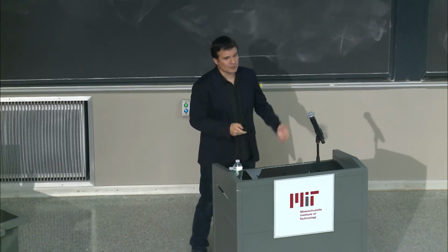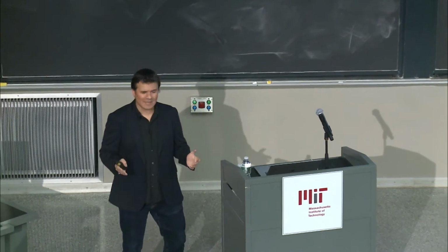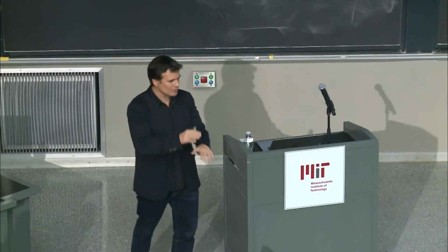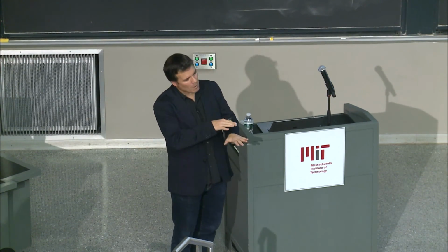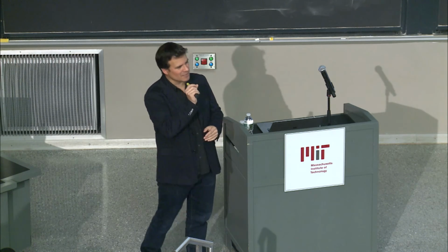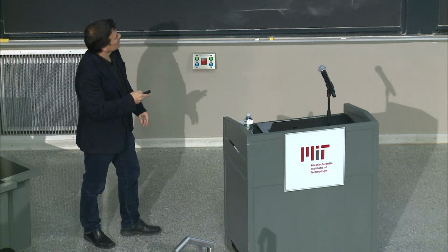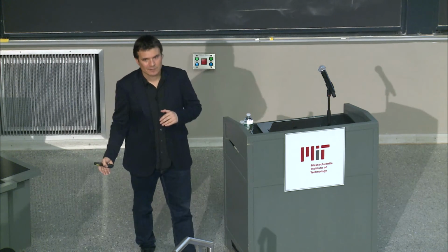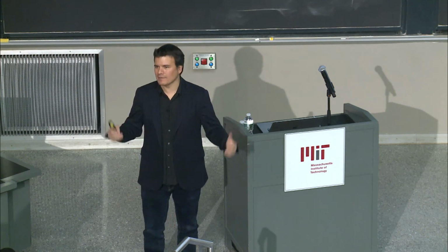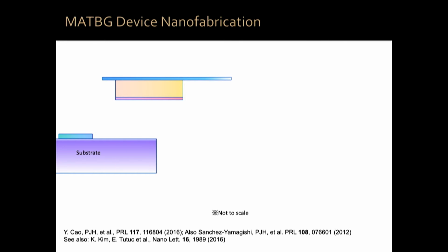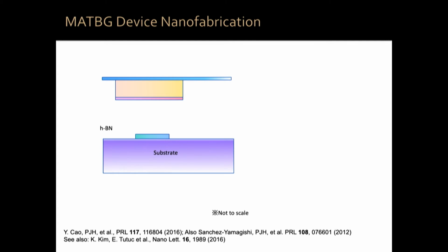Now, before I show you some data, a lot of people always ask me how do you actually do this? How do you put the two graphene sheets on top of each other at 1.1 degrees? The emphasis is on the 0.1. It's important, actually. So let me tell you how we do this. It's at the same time simpler and harder than you may think. We start with a glass slide which has a sticky polymer stack on it. Then we bring a substrate which has hexagonal boron nitride on it. Hexagonal boron nitride is a layered material, ultra flat.